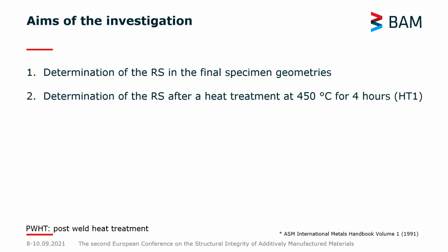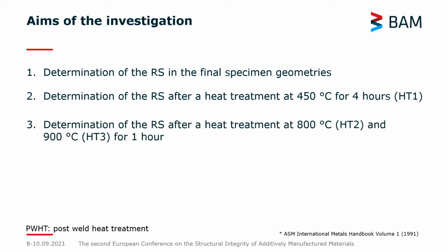Then we will focus on the residual stress distribution after the first heat treatment at 450 degrees for 4 hours in the SENB geometry, with the aim to further look into how the residual stress relaxed when you apply an additional heat treatment at 800 degrees and 900 degrees for 1 hour.